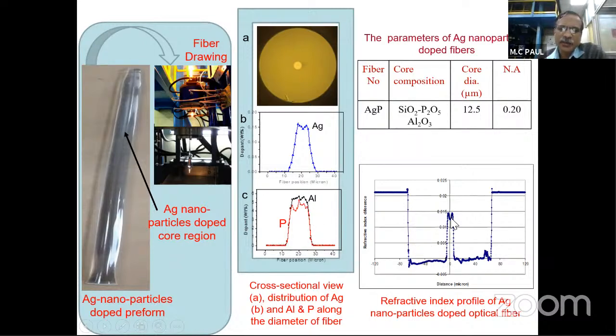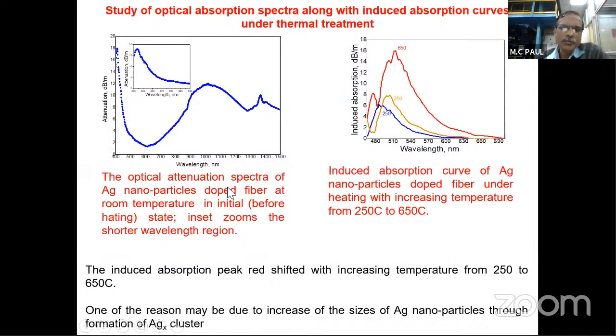This is the refractive index profile of the fiber. What is the refractive index of the core and cladding layer? From this, the core diameter is 12.5 micron and NA around 0.2. And this is the absorption property which we have measured at room temperature. After that, we increased the temperature from 250 to 650 degrees centigrade, and the absorption gradually increases and shifts to a higher wavelength side. This is because with increasing temperature, the size of the silver nanoparticle increases from most probably silver nano clusters. And we have done this.